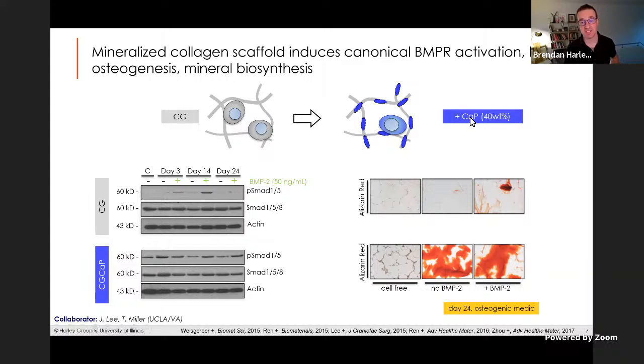So this material we designed in a number of ways, but one of the primary ones, and we see on the bottom here, these are mineralized materials whose structure and chemistry is such that it instructs the stem cells inside of them to turn into bone cells without us having to use that growth factor. We can see that on the right, where on these non-mineralized scaffolds you see very little red, which is a marker for new bone formation in the laboratory.